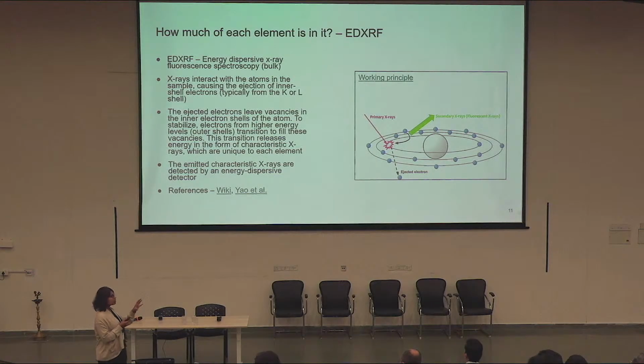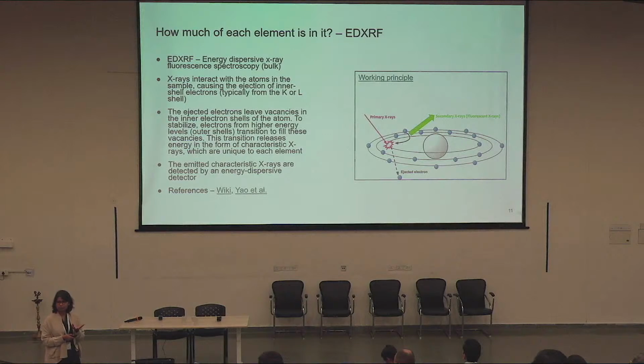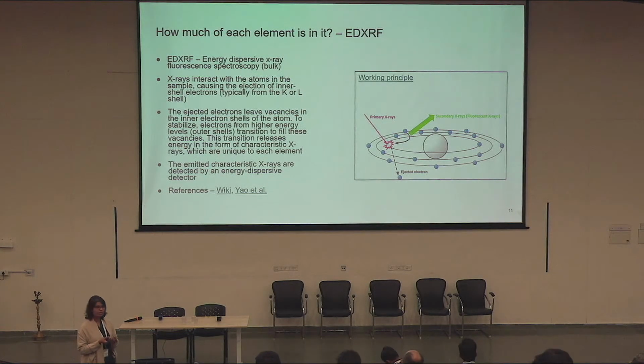So this is something that is close enough to the X-ray diffraction that we discussed. In a way, what happens is that you have a sample. There is no need for digestion or any pre-treatment of the sample. You just take your solid sample and then you just put some X-rays on it. So when you put X-ray, the X-ray has enough energy to excite one of the electrons in your inner shell of the elements that are present in your sample. And that electron is ejected out of the system.